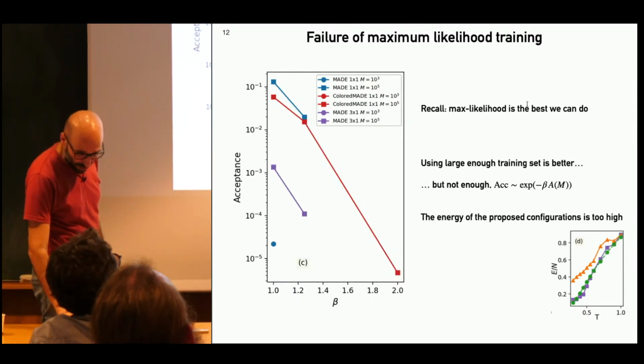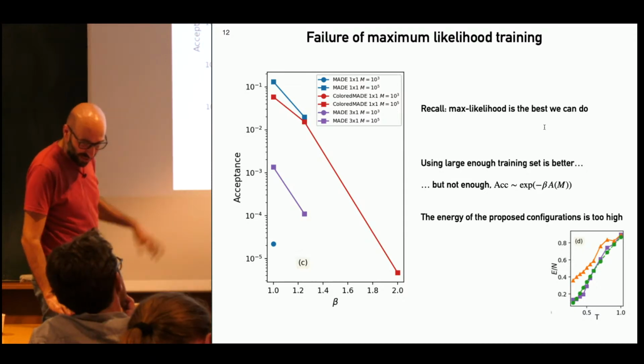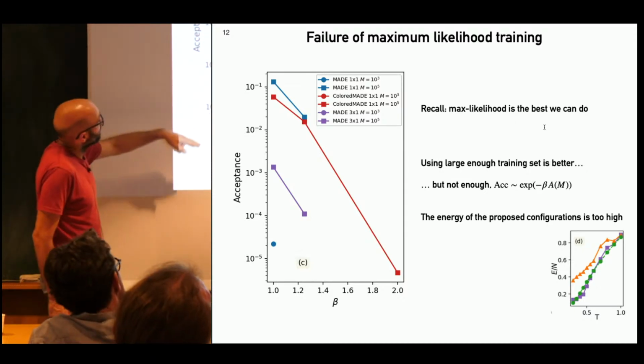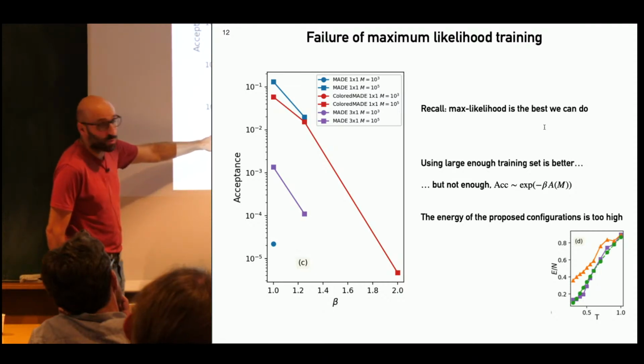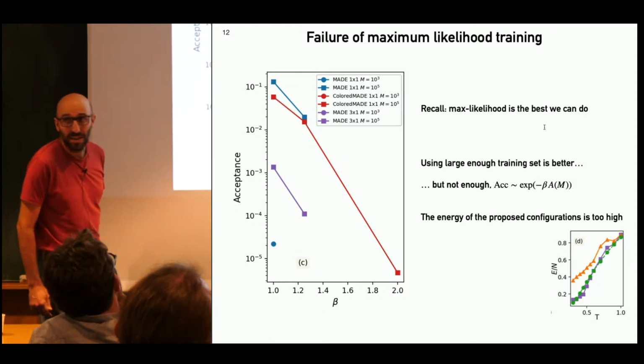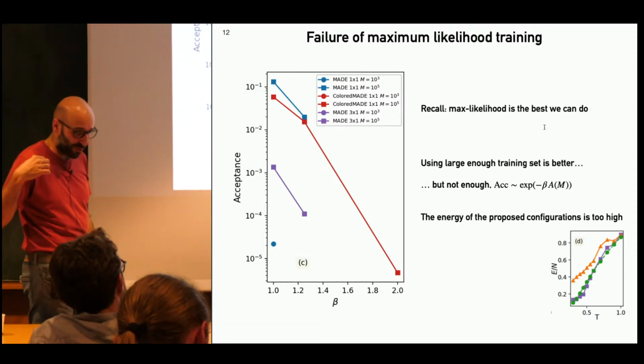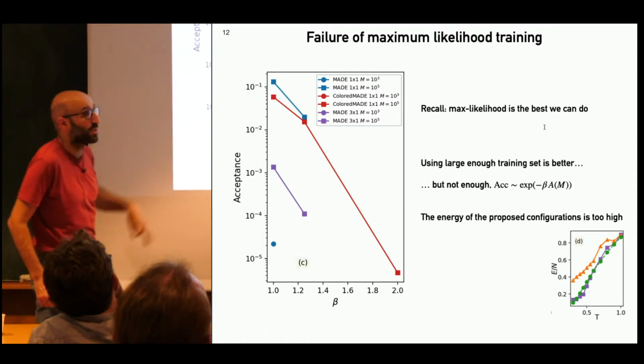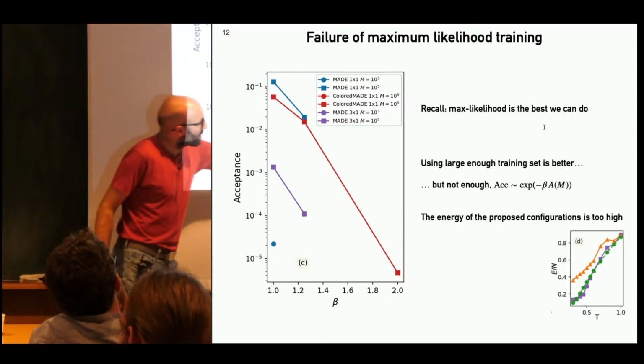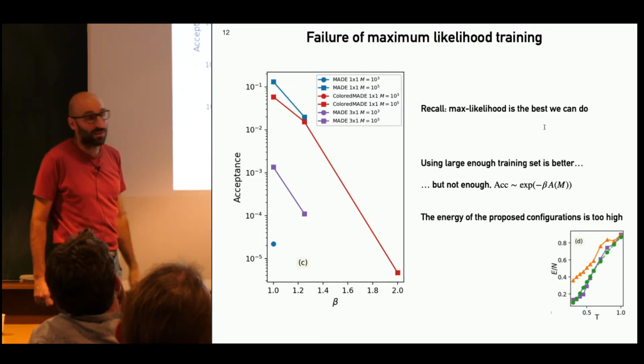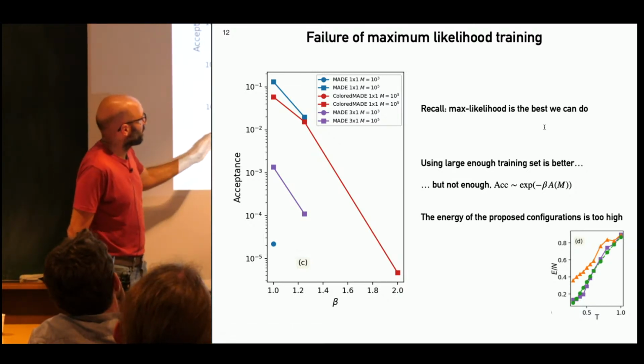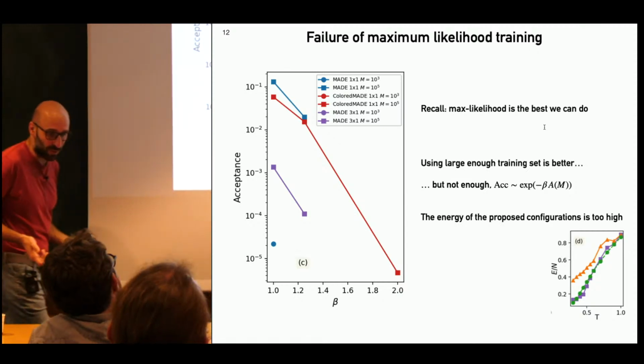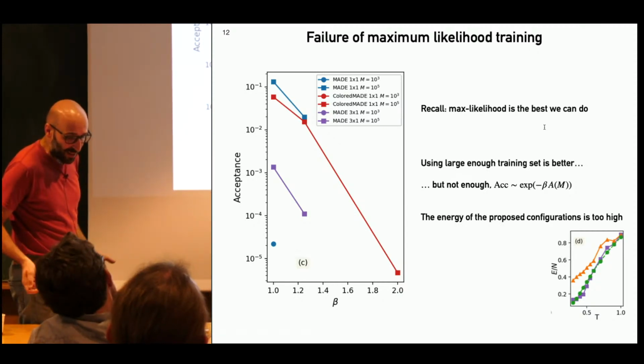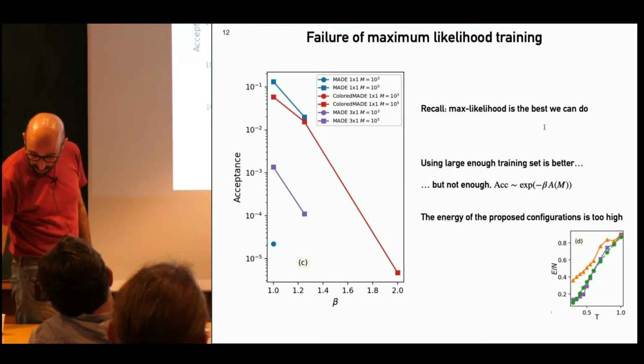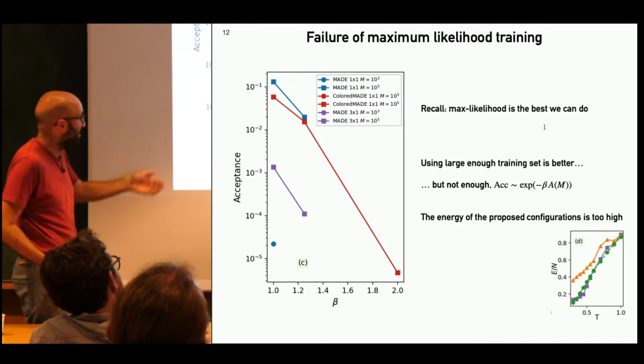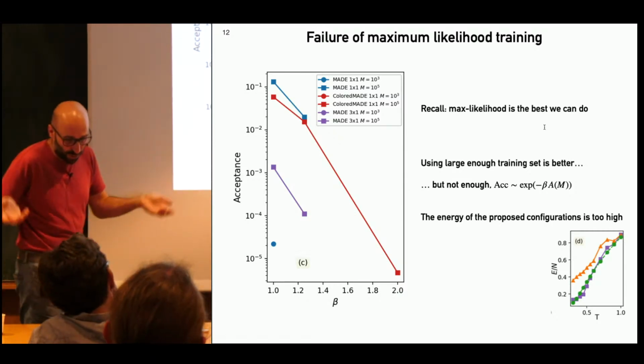Recall that this is the best we can do for a given architecture. What happens is that if you fix the temperature to 1 and you increase the training set, as in the spin glass I showed before, the acceptance rate goes up, so that's good. But then when you lower temperature, it goes down exponentially. So this means that if you want to lower the temperature, you need more and more training samples to get a decent acceptance rate. You could think maybe I can use more expressive models to have a better fit, but this would probably require even more training data.